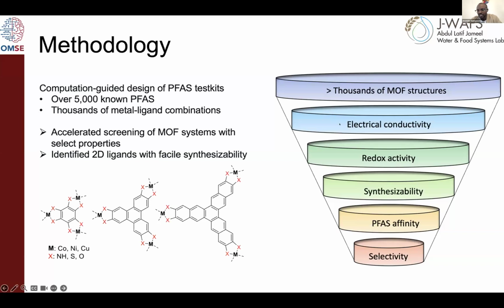But here we're interested in the ones that are electrically conductive because we want to be able to read out the response from PFAS contact. And here we also can use the porosity and the tunability of MOFs to get other parameters such as the affinity and also the selectivity. Throughout our screening, we've landed on a few building blocks. So these structures that I'm showing here, maybe I need to get my laser pointer, if that makes it easier. Maybe not. I can use my pointer.